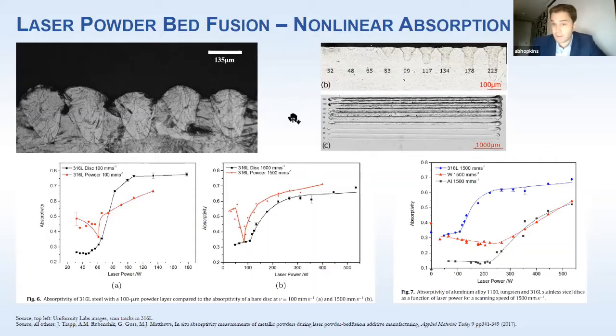It's also tremendously dependent on the powder, in a way that you can have scan tracks that are 4 times as large if you have different powder properties with all other qualities being the same. Particularly if you use denser powder, if you're able to get the melt pool cooler. That's been shown. So here on the bottom left, I'm just showing some absorptivity properties. This is in a disk. That's the black line at 100 millimeters per second at different powers.